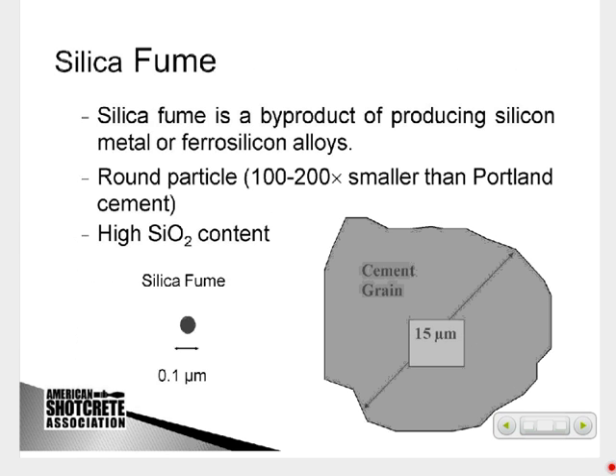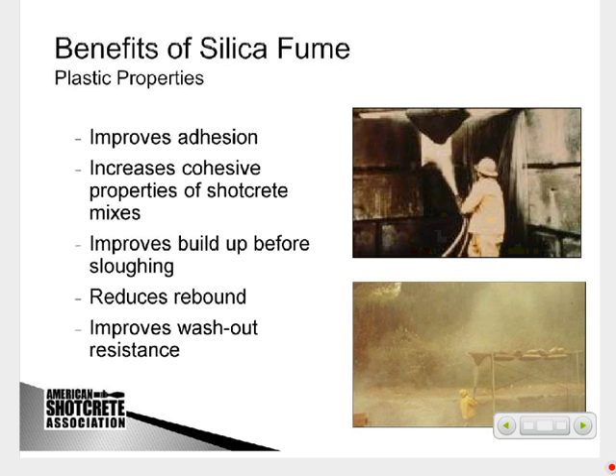We do use silica fume. This is a very small particle. It improves the adhesion. You can see those pictures. You can see like a beehive shape, and it's not a great picture, but they've shot almost a foot of thickness of shotcrete in place in one layer.